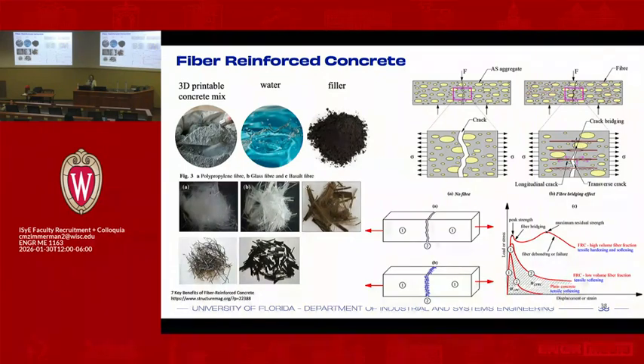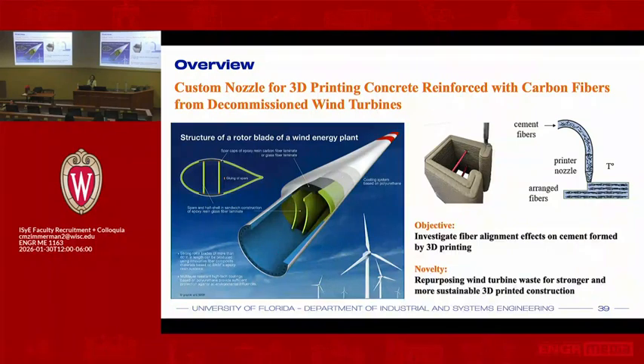In the civil engineering world, they struggle with the soundness of this type of composites aspect. But if you notice from this picture here, looking at the aggregates and the crack formation in comparison to fibers, it's going to be very important to have some control on the directionality of the fiber to be able to restrain that crack formation. So what we started looking into is customizing the nozzle to introduce those fibers into it and seeing whether we can actually affect the directionality and get the strength associated with that reinforcement. And could it actually be comparable to your traditional masonry?